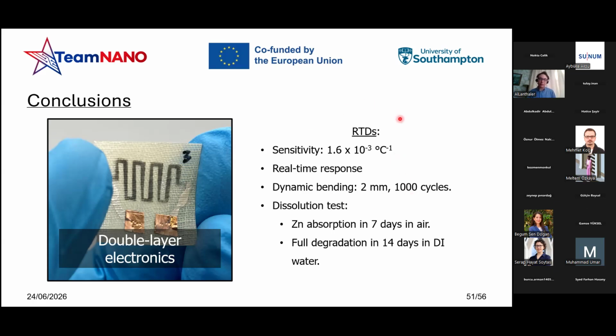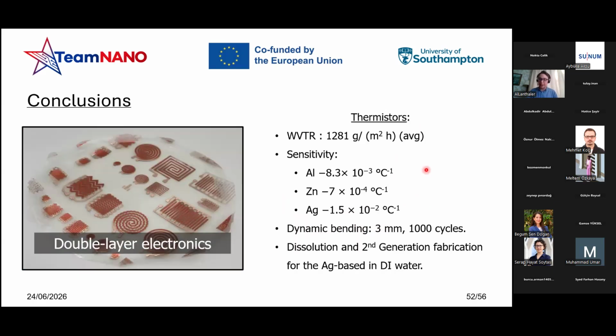and a fully recyclable device, being able to be absorbed in 7 days in air, and achieving a full degradation in 14 days in water. For the thermistor one, we were still able to achieve a very breathable device. On average, it is 1 kg per square meter per hour of water vapor transmission rate. The sensitivity again is comparable with the literature for the same IGZO-based device.